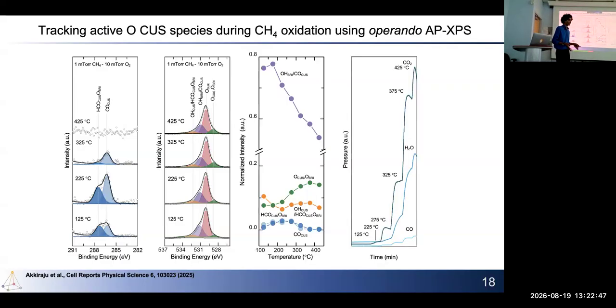Within the setup, we are also able to track the gaseous products using a mass spec. We see that by the time we get to 425, you have a lot of CO2 being formed and also a minor amount of CO, suggesting that iridium oxide was able to not only activate methane at a relatively low temperature, but also lead to complete conversion to CO and CO2.